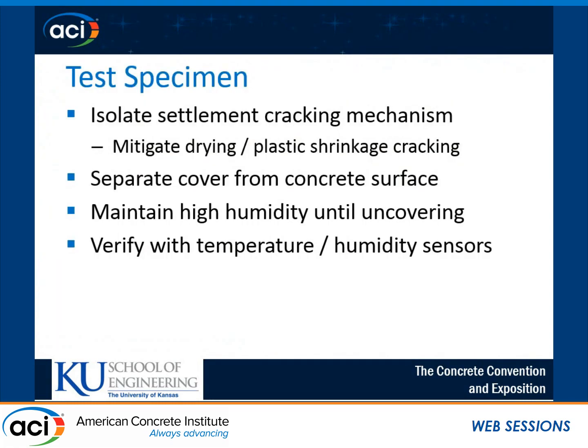And this is to help mitigate other factors that can come into play in that first 24 hours that can cause cracking. So we just want to isolate settlement cracking by itself and not have drying shrinkage or any other issues with surface defects come into play. We also want to make sure that we maintain a high humidity during curing, and we can verify this with temperature and humidity sensors that we place on the forms, and we can monitor that throughout the curing period.